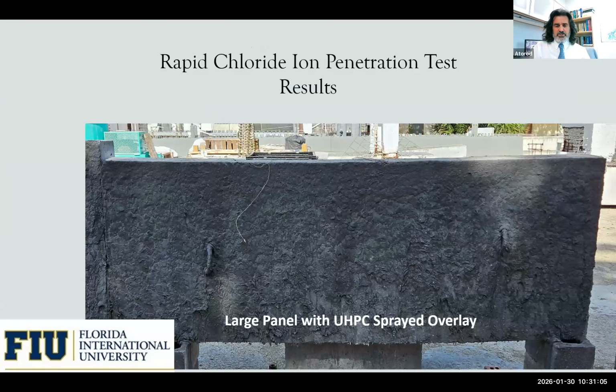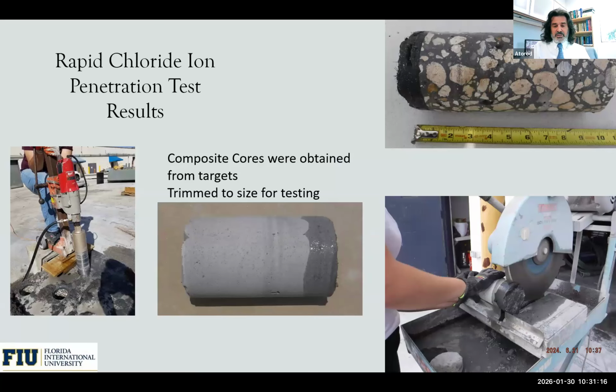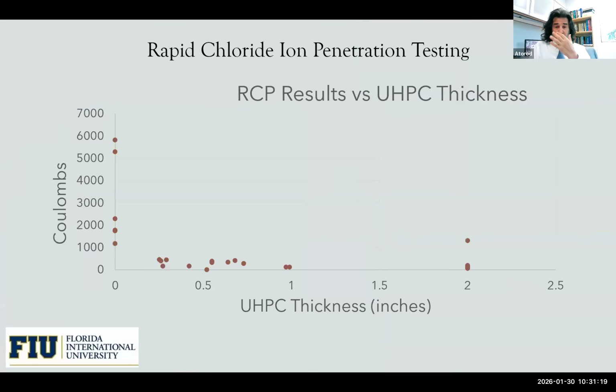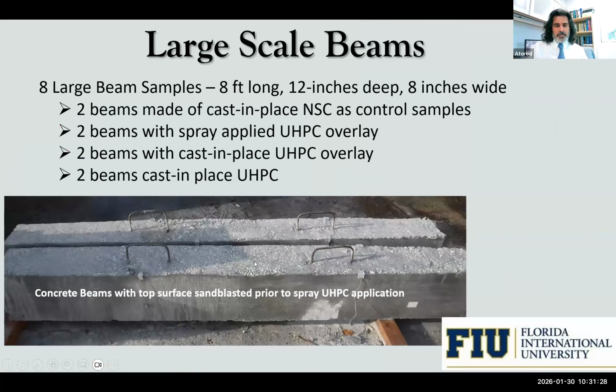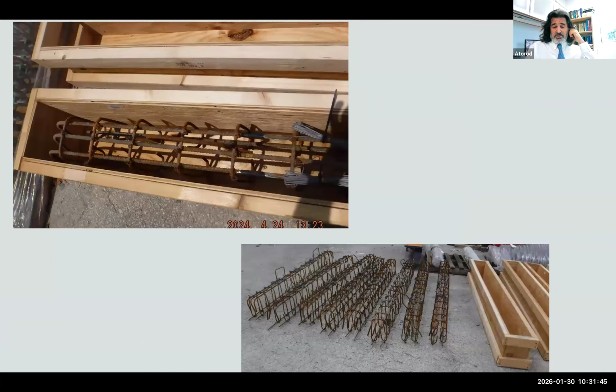These are some data; I will go through them. We've also done sprayed or cast in place UHPC on small specimens and then done the RCP test. You can see how the RCP value reduces very significantly. We've also done some relatively large scale tests: 8 foot long, 12 inch by 8 inch beams, cast with UHPC or sprayed with UHPC, and then tested under flexure. And these are some of the beams.